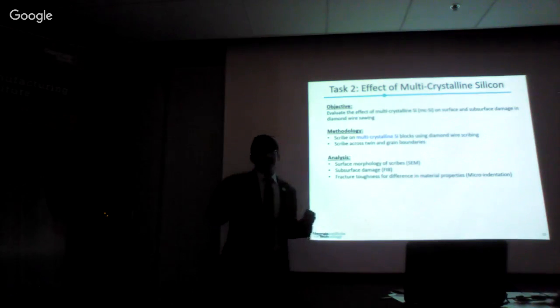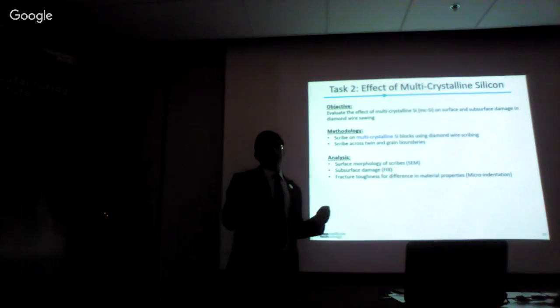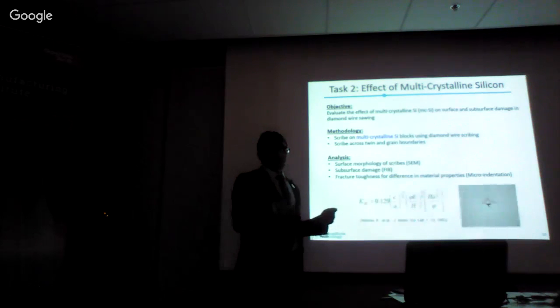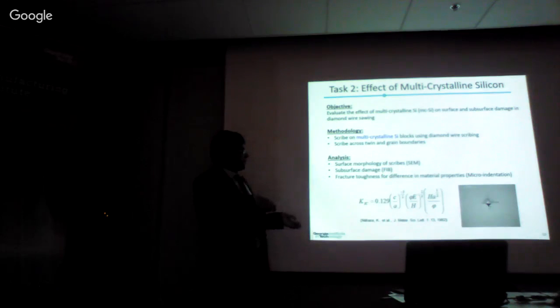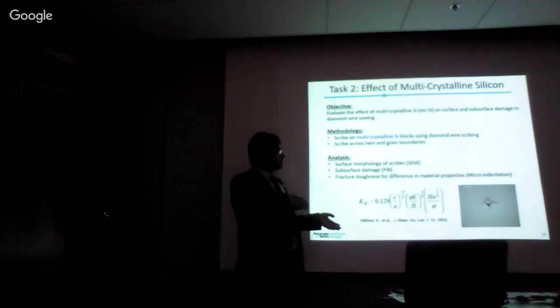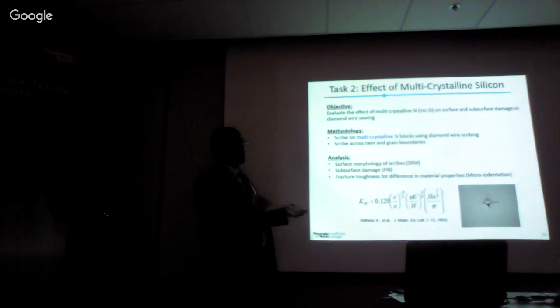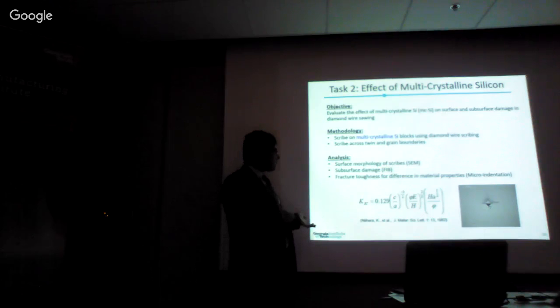find the fracture toughness using micro hardness indentation or Vickers indentation. The indentation creates a diamond shape like this, where we also see cracks emanating from the corners. The crack length C is measured. The value of half of the diagonal of the indent, A, is measured, and C and A are parameters which go into the equation with material properties like modulus of elasticity and hardness, and some factors which are constant, to give the fracture toughness K1C.